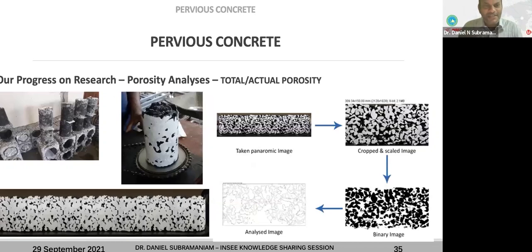This is the image analysis that I was talking about. You can see here, we cast cubes, and then we take the core samples. Each core sample is 100 millimeter diameter. And then we spray paint with black color, and we hand paint the cut surface. So you have a distinction between the pores and the solid surface of the curved surface of the core. And then we take a panoramic view of the digital image.